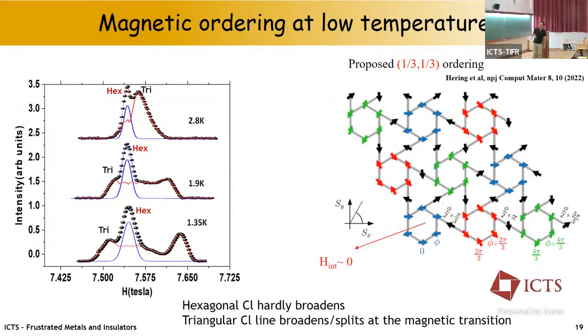And the interesting point is that if you look at the center of one of these hexagons, any of them, of the perfect hexagon, the hyperfine field will be 0. Because we have two sets of three spins which are nearly anti-parallel. So the sum of the spins is basically close to 0, so the internal field at the center will be 0. And that fits nicely with the fact that the hexagonal side is not changing much through the transition.